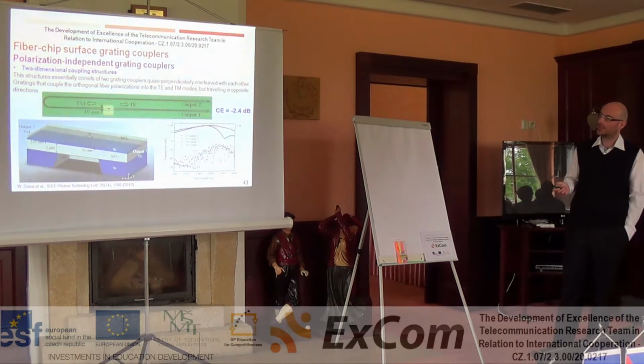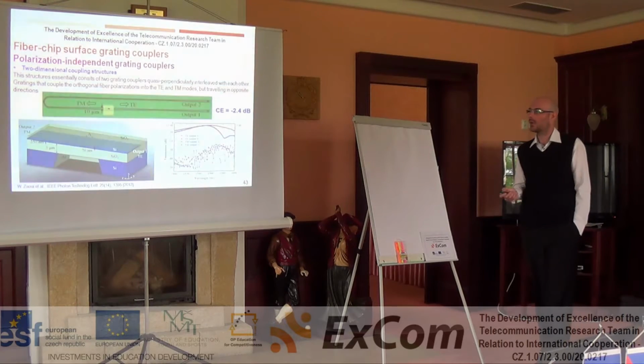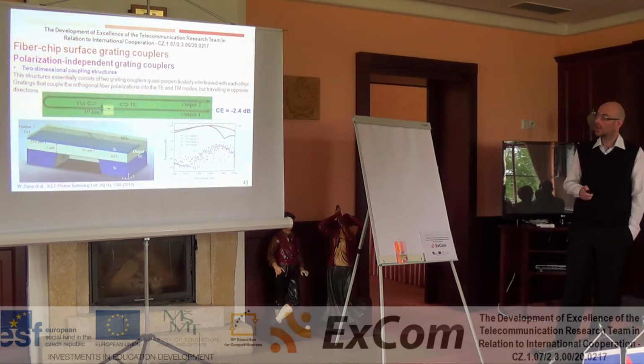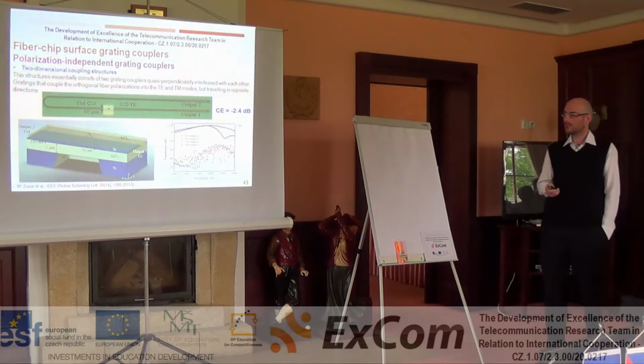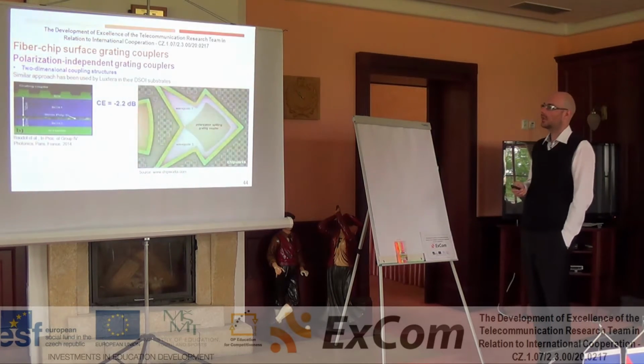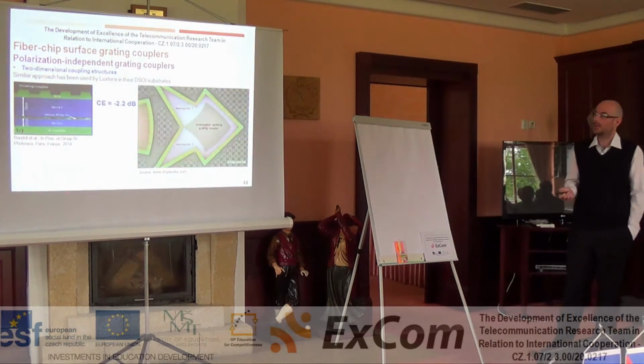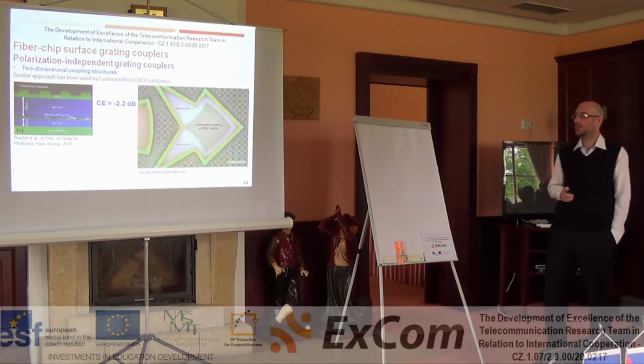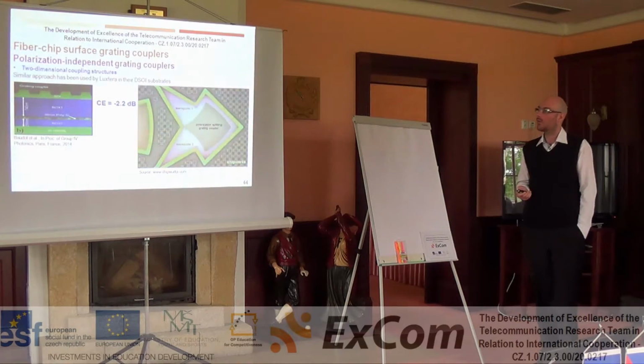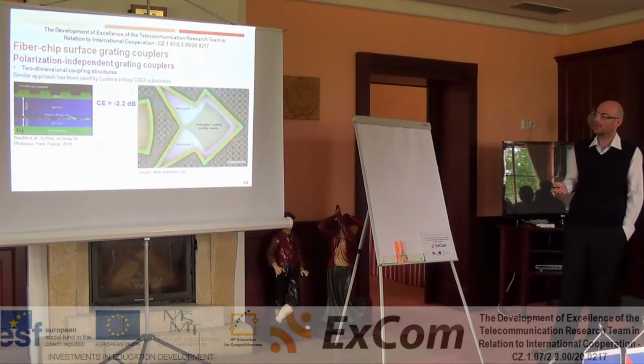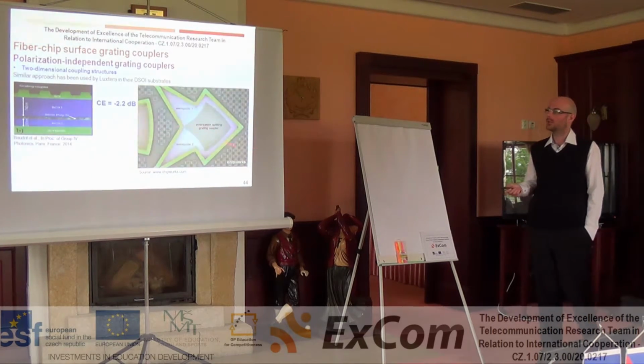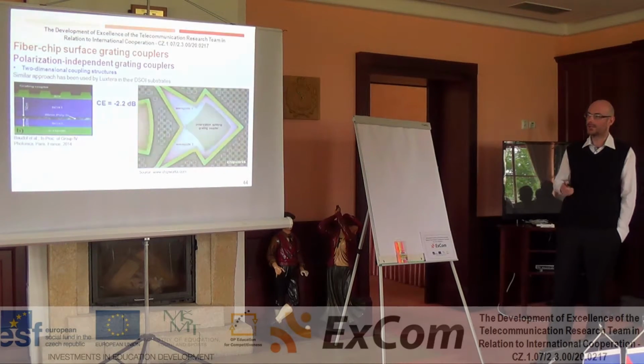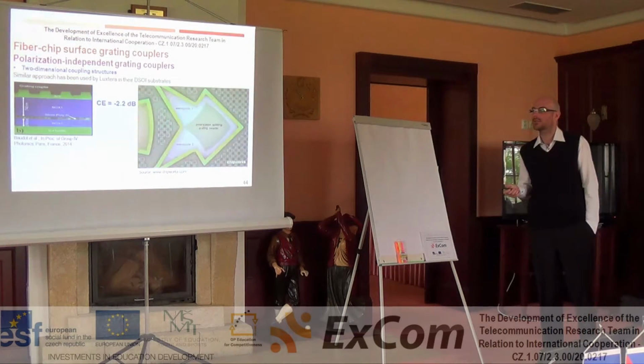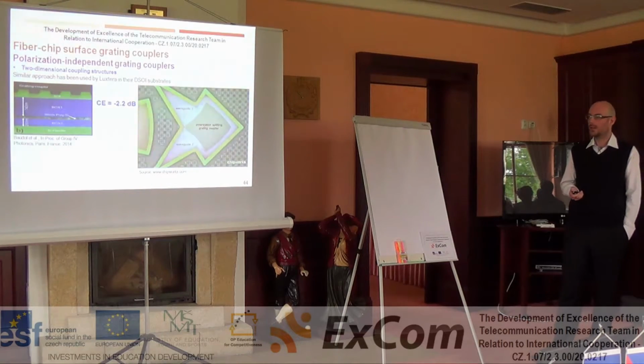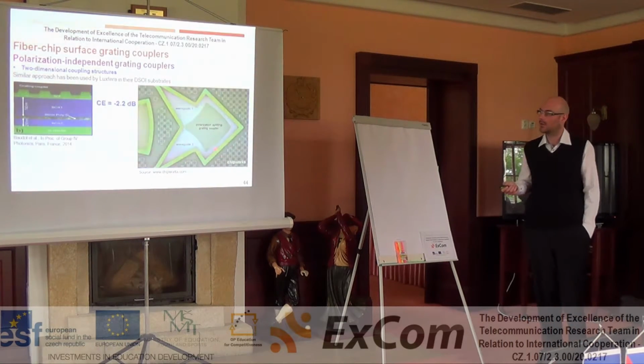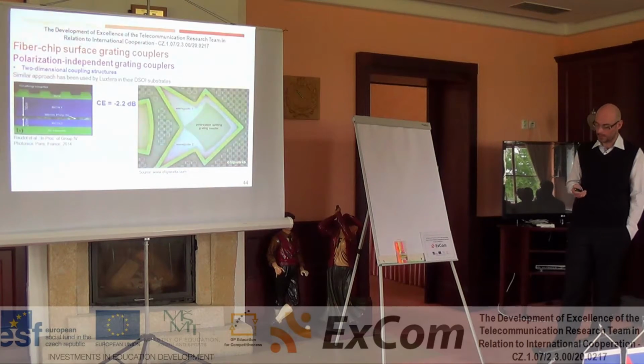They achieved a very nice coupling efficiency for both polarizations at the level of -2.4 dB. A similar approach has been adopted by Luxtera in their customized silicon on insulator wafer. Also, they interleave two grating couplers to couple light with TE and TM polarization at the same time. They achieved -2.2 dB coupling efficiency for their polarization splitting grating couplers.